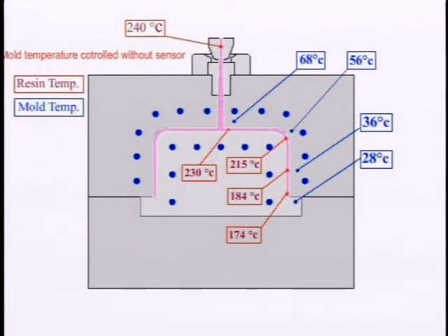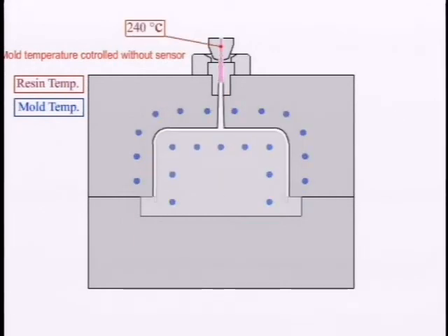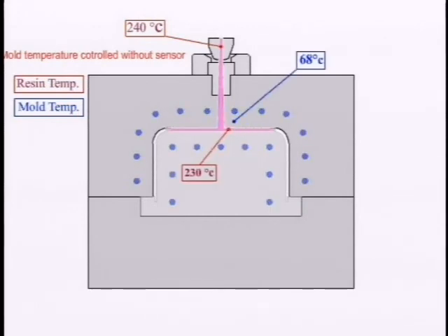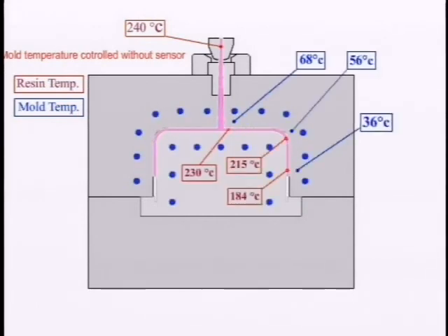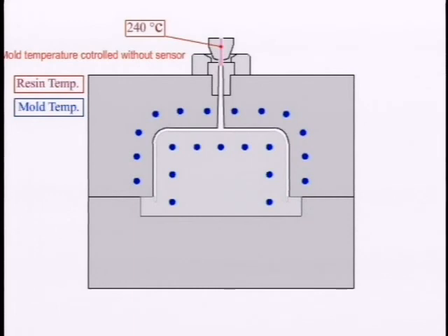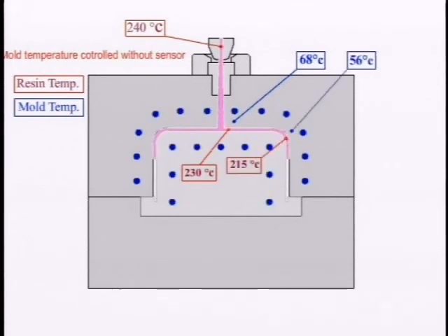For that reason, the mold temperature around the gate shows 68 degrees, and the edge shows 28 degrees. In case of the resin fill-in, the heat capacity decreases bit by bit according to the distance. So the gate is filled in with a temperature of 240 degrees, and the edge is 174 degrees.